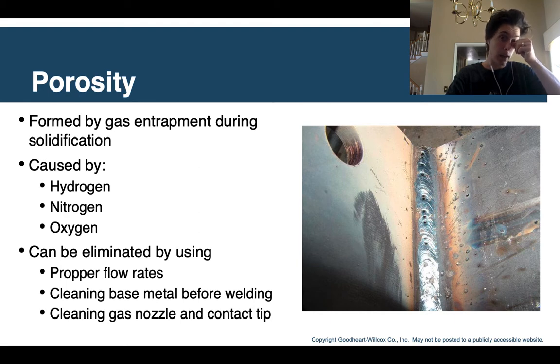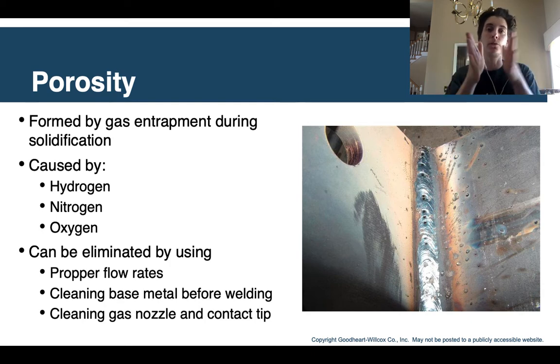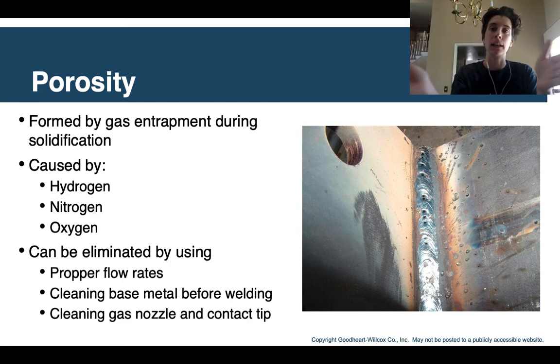And I said you should check your flow rate, but I'm changing that. The first thing you should always check if you're having a problem with your weld is your gas nozzle and the contact tip, because the end of the contact tip also accumulates spatter on the end, so you want to clean that off as well. It can cause a lot of problems. It disrupts the gas flow. Those pieces of spatter can fall out into your weld and cause problems with porosity. And you can also fuse your electrode wire. It's not going to feed out cleanly. It's going to stick to the spatter that's built up on your contact tip. So all of that is something you just have to periodically check and clean.